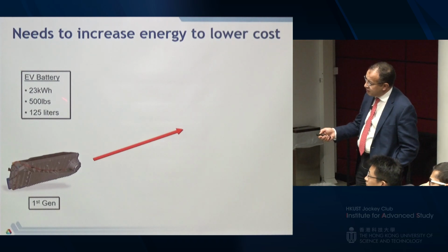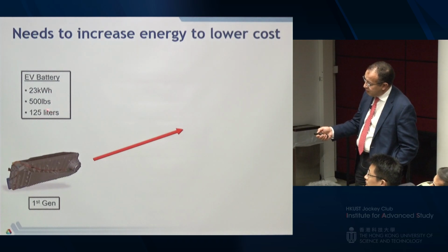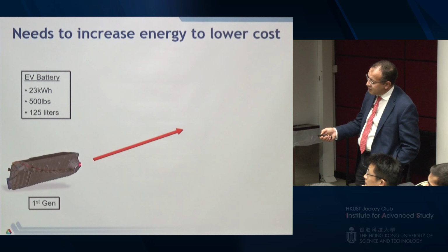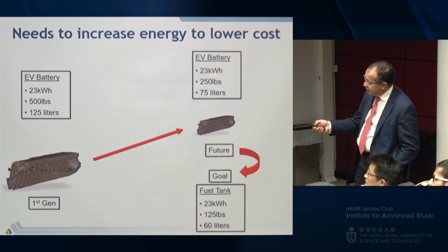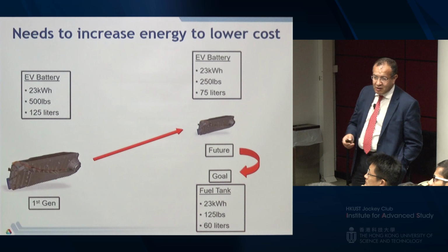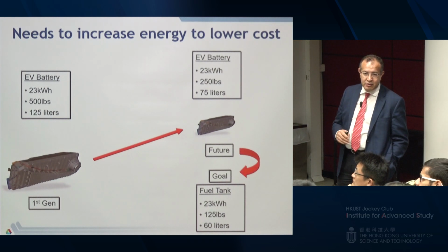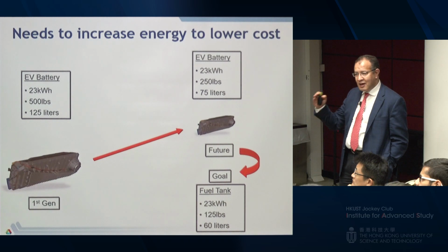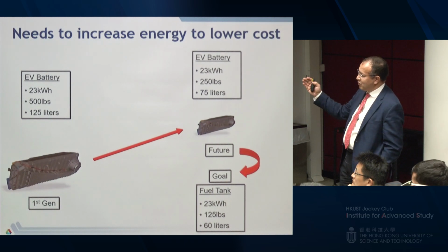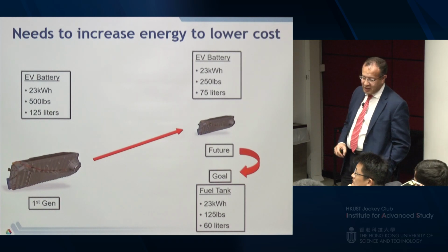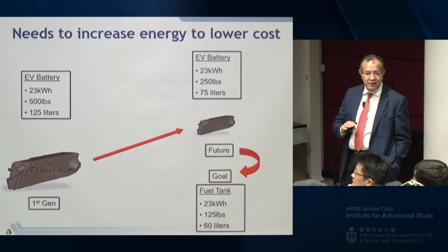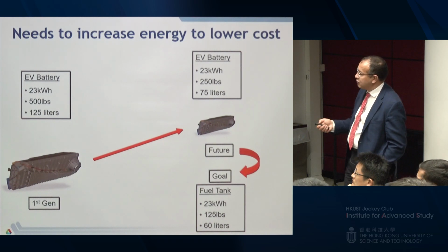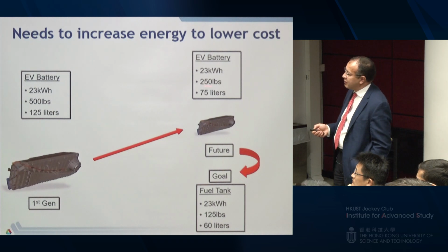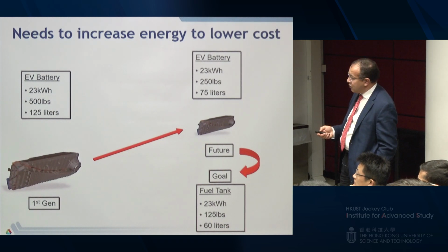If you have a battery with that much energy, with that much volume and weight, this is basically a Nissan Leaf pack. If you are able to increase the energy density of the chemistry inside this battery, you can make it smaller, but yet have the same energy at the pack level. Now you have less material across the board. That's a real way of reducing the cost. Remember that. Going from a cathode A to a cathode B, like moving from a cobalt system to an iron-based system, will not make a major impact because the cost of a cathode is only 10% at the pack level. So remember that if you really want to make an impact on cost, you have to increase the energy of the whole system. So how to increase the energy?